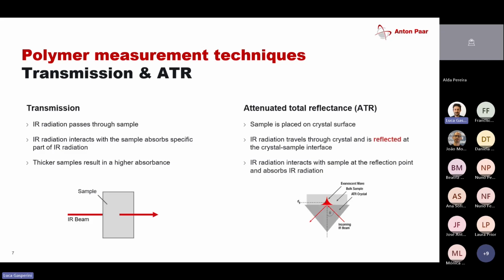And then we also have, and this is the most commonly used method, attenuated total reflectance, called ATR. We have both of the measurement cells here. So what's the difference? Here we just shine through the sample, and in this case we place the sample onto a crystal. The crystal can be either diamond, germanium, or zinc selenide, depending on the spectral range you want to achieve, and also on the refractive index. This works with total reflectance. One thing to keep in mind is that the refractive index of the crystal must be higher than that of the sample, because otherwise I don't have a total reflection, and in this case I don't get any signal from the sample, or not enough signal.